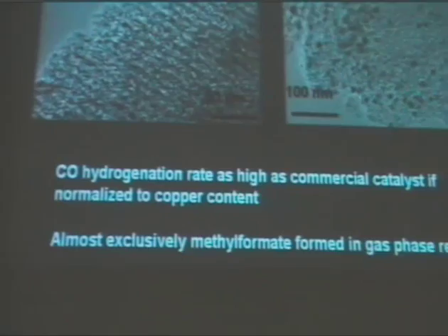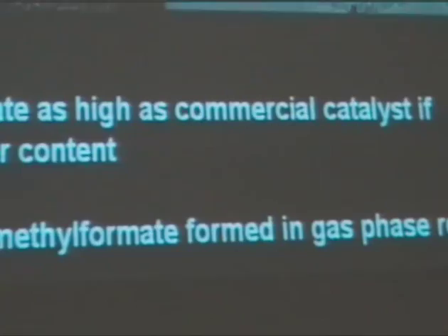Finally, we wanted to compare the system with the heterogeneous system, and we deposited these copper colloids on the mesoporous CMK-5 carbon. This is what it looks like before reaction. So this is really barely visible. These are 2-3 nanometer copper particles here. On the porous support after reaction, they grow by about a factor of 3.